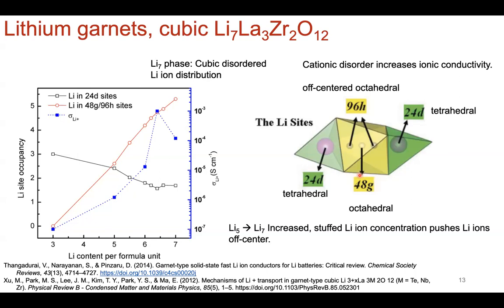And the fact that they're off-site like that, now they're motivated to also start migrating, and the activation energy comes down because of the Coulombic interaction, the lithium-lithium repulsion. The lithium ions are too close together, they're motivated to actually move and migrate. Okay, so that drives up the ion conductivity of the system, because when you bring down the activation energy, right, you increase the jump frequency as well.